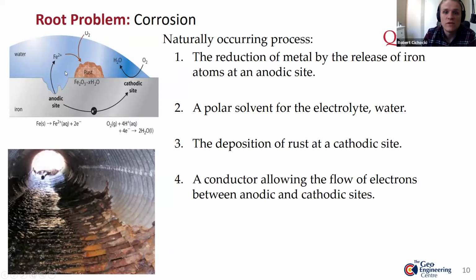Next, we need a polar solvent for the iron atom to dissolve into where the reaction occurs. Then we need the deposition of rust at a cathodic site. So the iron atom reacts with the oxygen molecule and iron oxide is deposited on the surface of the material. And we also need a conductor allowing the flow of electrons to go between the anodic site and the cathodic site. So when the iron is deposited as iron oxide on the surface of the material, it can regain its electron. So the metal acts as a conductor between the two sites and allows the iron to regain its electron.